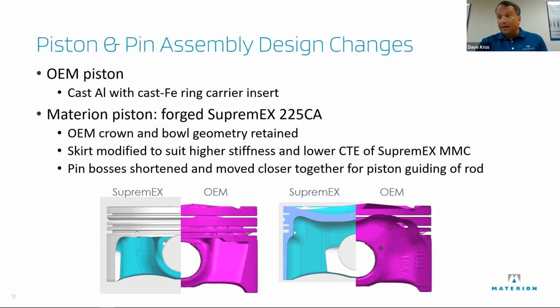We also, because of not having the ring groove insert in there, which adds about 20 grams to the piston because of the difference in density from the cast iron to the aluminum, we were able to move the groove up quite a bit and get rid of crevice volume, which theoretically should increase your efficiency, decrease fuel consumption, because whatever gets down in the crevice doesn't get burned.